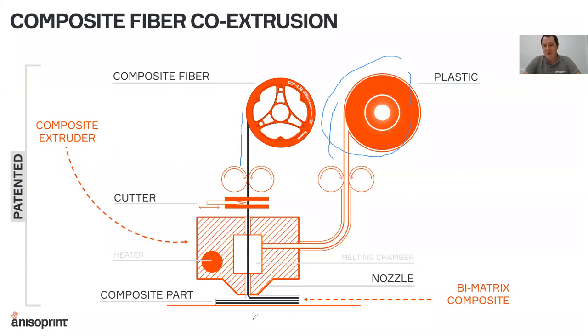I will stop once again on this term, why it is called a bi-matrix material. It's a composite material, of course, which has the reinforcing fiber material inside, and two matrices. One matrix is the resin that is inside the fiber tow, inside the composite fiber, the resin which bonds microfilaments inside the fiber. And the second material is a plastic material, which we call the main matrix material, which bonds these composite fibers together. So in the final composite, there are actually three components: fiber, resin, and plastic, and two interfaces. There is one interface between the fiber and the resin, and an interface between the resin and the plastic. There is no interface between fiber and plastic.